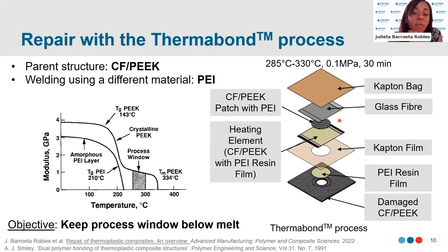Now, this heating element was made out of one layer of carbon fiber PEEK surrounded by PEI resin film on each side. And the patch was made out of carbon fiber PEEK with PEI at the location where it would interface with the heating element. Both the heating element and the carbon fiber PEEK patch were processed at 380 degrees Celsius, which is the processing temperature of PEEK. Now, the idea was to pre-process these two components and then provide them to a repair station. The repair was then conducted at a maximum temperature of 330 degrees Celsius for 30 minutes. So this was possible thanks to the fact that this PEI layer was used together with PEEK.